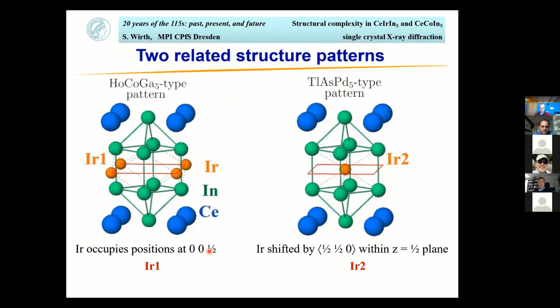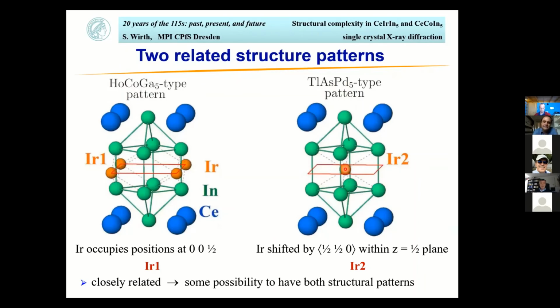Now, and that's where Yuri, with his profound knowledge of crystal structure, comes into play. He pointed out that beside the holmium cobalt gallium 5 type of pattern, there's another type of pattern, which is called thallium arsenic palladium type pattern. And the only difference you see here is actually in the location of the iridium. Look here at the z = 1/2 plane. Here you have the iridium at the corners, and here you just shift this along the diagonal to the center, and then you have the iridium here. So these two structures are really very similar. So there is some possibility that we have actually both structural patterns in our sample.